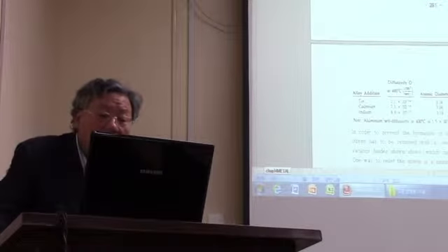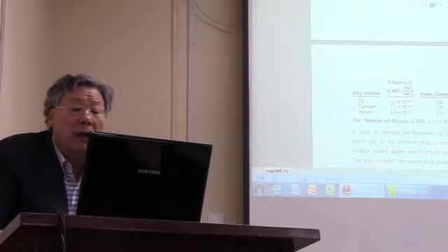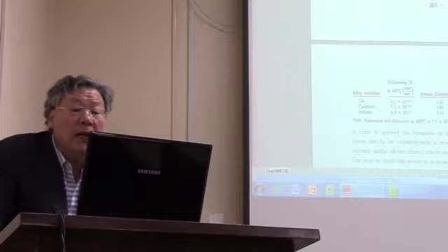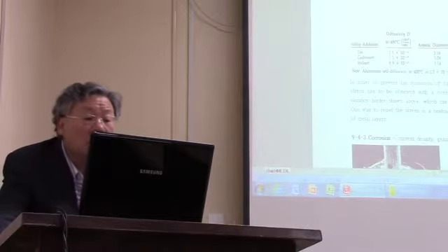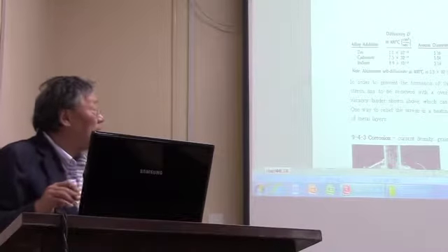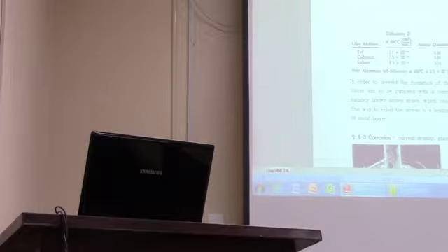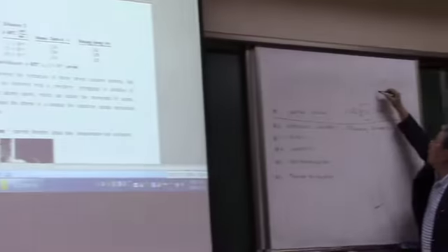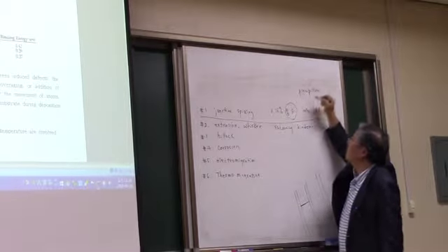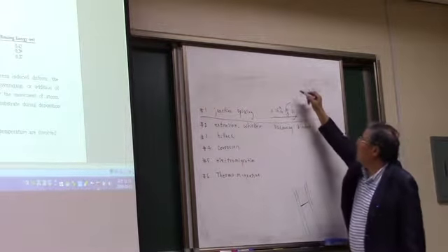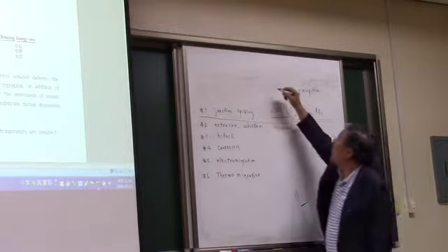So what are the elements for the vacancy binders? Tin, cadmium, indium, and typically we are going to add a very little amount of these atoms. In the junction spiking case, with the silicon, we should not form a precipitation. Precipitation means we have to add the silicon below the solubility limit, right?